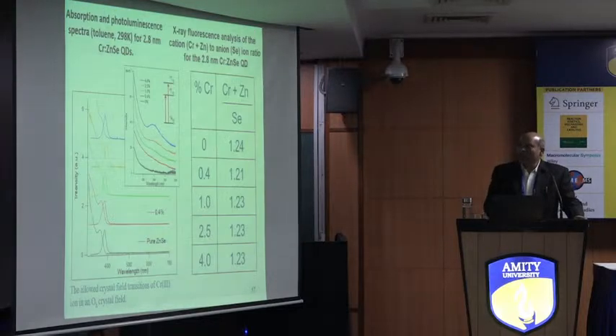We take the absorption spectra. You can see the peak is coming here systematically. If you enlarge this part, then you will get some hump also here. It is showing the chromium 3 signature. Then we take X-ray fluorescence, and we take the ratio. The ratio is not going to change.